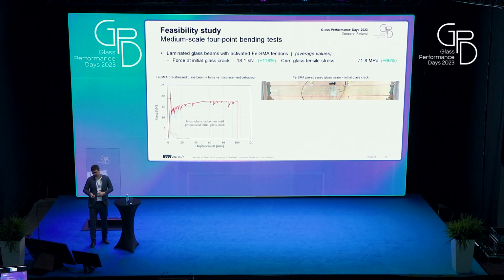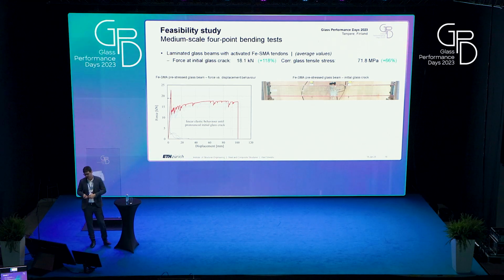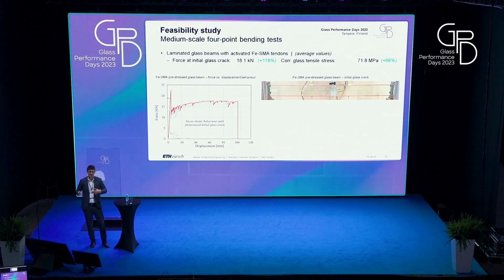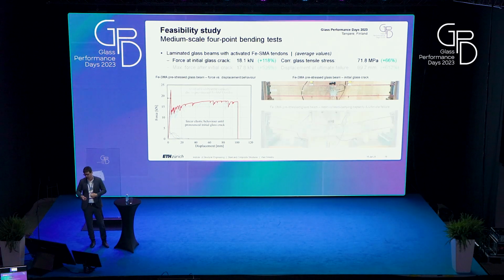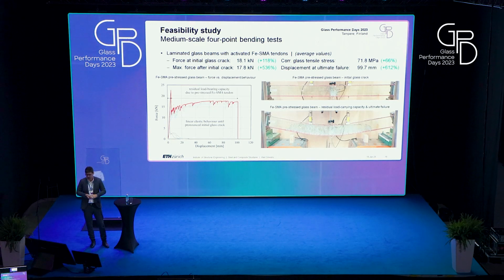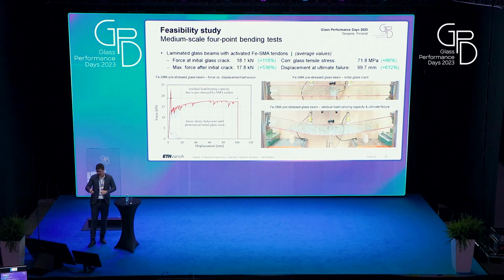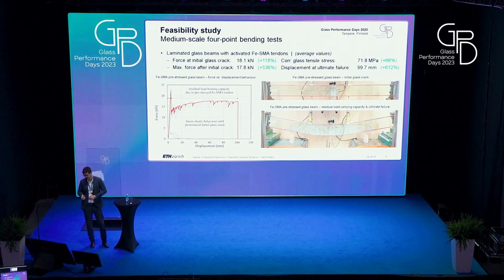However, if we look at the ones with activated tendons, we were able to further increase the initial glass crack. So this is mainly the advantage of the post-tensioning. But afterwards, the behavior was pretty similar to the beams without activation. And here, as I said, we had to stop the tests at 10 centimeters deflection.